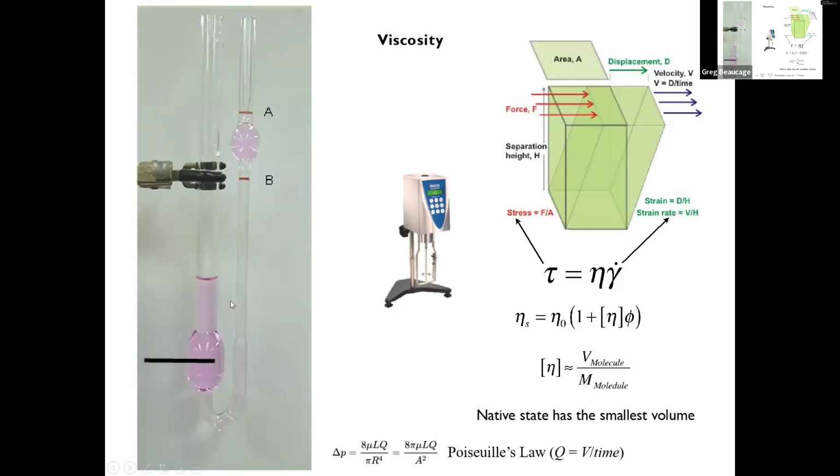And all right, so the viscosity depends on the Arrhenius equation, in other words, it's deeply dependent on temperature. So if you do this measurement, you have to be really careful what the temperature is, because an exponential dependence of viscosity on temperature is going to be stronger than this dependence. Right, so usually this thing will be immersed in a big oil bath, like a silicone oil bath, and then it's kept at a constant temperature to do it. So that makes it really messy. Otherwise, it's a really simple measurement.